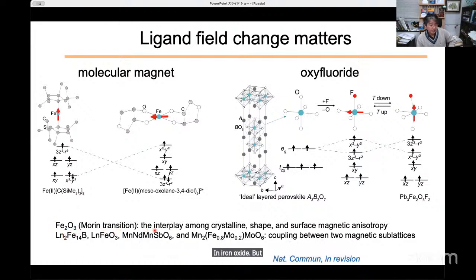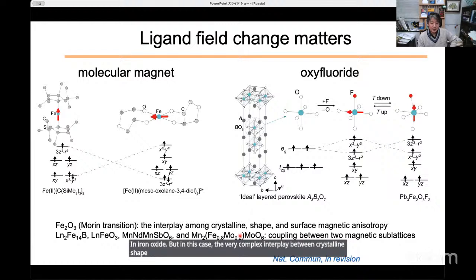But in this case, the very complex interplay between crystalline shape, crystalline size, and surface magnetic anisotropy is involved. In this type of material, the coupling between two magnetic sublattices is important. For example, the iron sublattice and the rare earth sublattice form different spin orientations. The interactions between the two can give rise to the spin orientations. But in our case, the simple consideration of the crystal structure can predict or explain the spin orientation switchings.